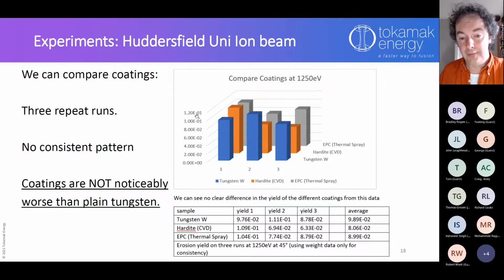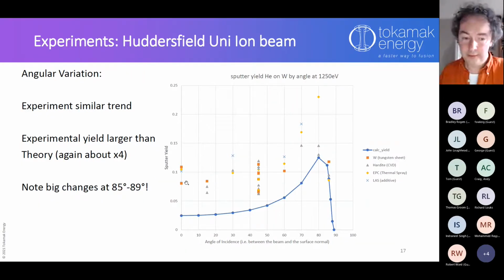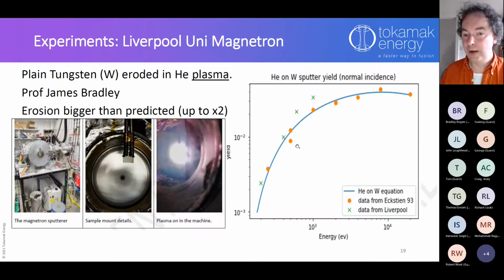So this could be why some of these, the additive manufacturing samples, are these crosses. In a few cases here, that has a slightly higher yield than the other ones done in the same experiment, because we run 3 samples at once. So this will be one run with different samples. In a few cases, this is probably the oxide coming off, which means it's eroded away quite quick, so you lose a bit of material. The other samples don't have that green oxide on, but it does clean up. They come out looking absolutely beautiful.